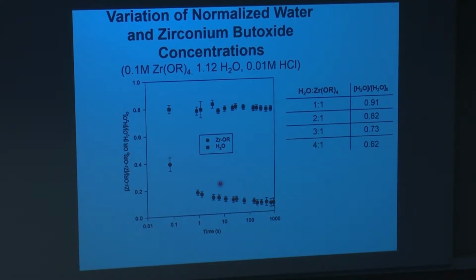So we're able to take our first measurement at about 80 milliseconds. And we're looking at the water remaining in the reaction divided by the initial concentration of water, and that quickly dropped to about 0.8 in about 80 milliseconds. And then the alkoxide group, about 60% of the alkoxide groups were removed within that first 80 milliseconds as well. And so what I show over here, basically, is what happens if you do the first hydrolysis, how much water should remain, 0.91, and if two water molecules are reacting with the alkoxide, how much water should remain, and so forth, all the way until all four of the alkoxide groups are hydrolyzed.